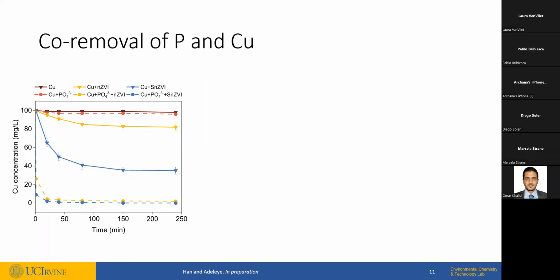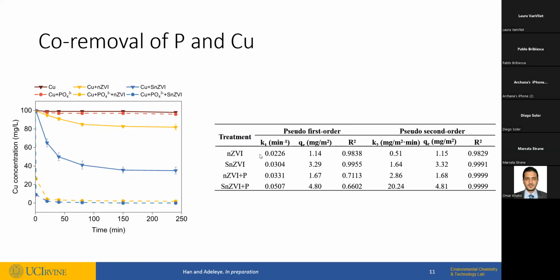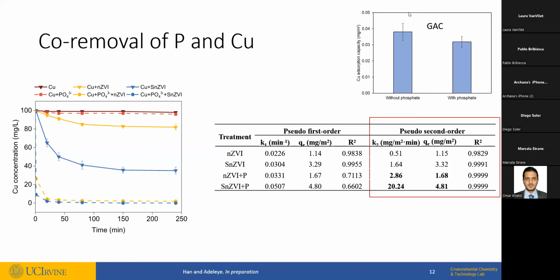It's like this system needs more contaminants to perform well, which is absolutely opposite what you would expect in a GAC system, like I already said. And again, this follows the pseudo-second order kinetics very well. Again, if we compare the performance of GAC for copper removal using the surface area normalization, the nanoparticles are at least 2 orders of magnitude better than GAC.